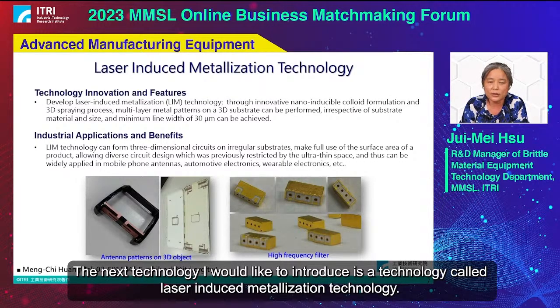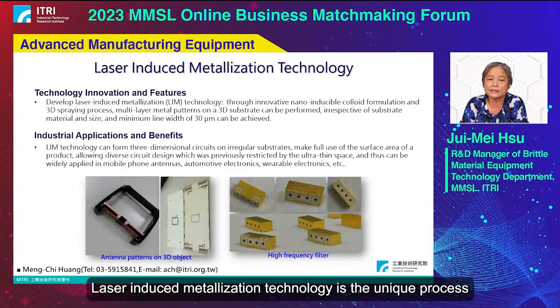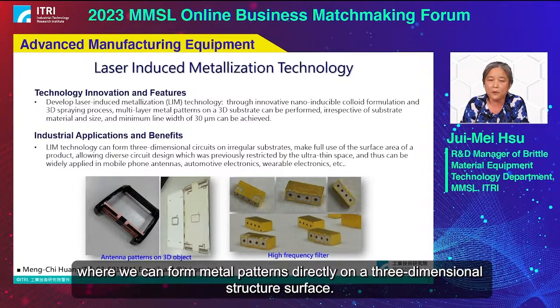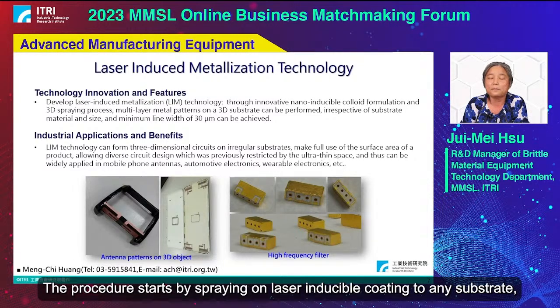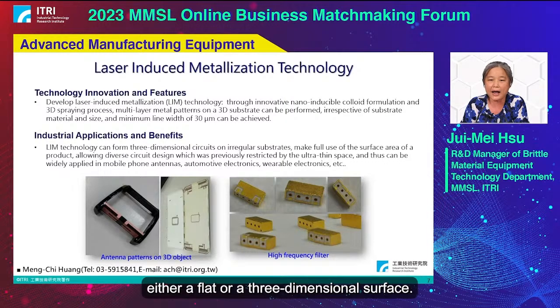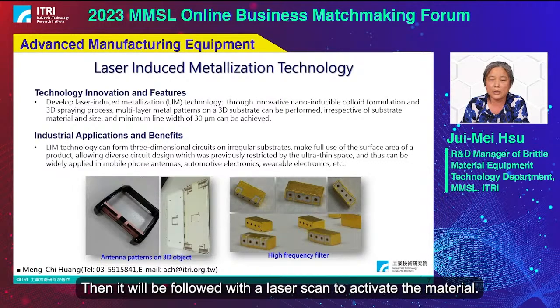The next technology I would like to introduce is a technology called laser-induced metallization technology. Laser-induced metallization technology is a unique process that we can form metal pattern directly on a three-dimensional structural surface. The procedure starts from spraying a laser-inducible coating onto any substrate, either flat or three-dimensional surface. Then it will be followed by a laser scan to activate the material.